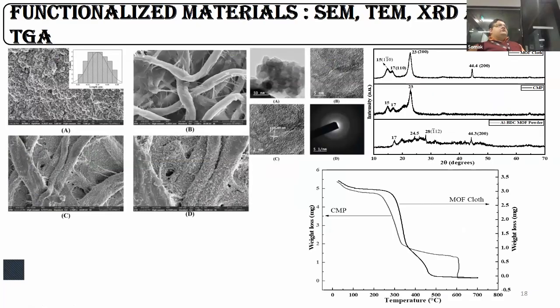Now, the reason for doing an XRD study over here is to ascertain whether, in the MOF cloth, the one present in carboxylated filter paper or carboxymethylated filter paper or the one present in the aluminum MOF, it's present in the main MOF cloth or not. We were able to see that most of the peaks were present. In this case, 44.3 is mainly the reference peak in the MOF powder, and this is present in the MOF cloth as well, with a slight deviation.